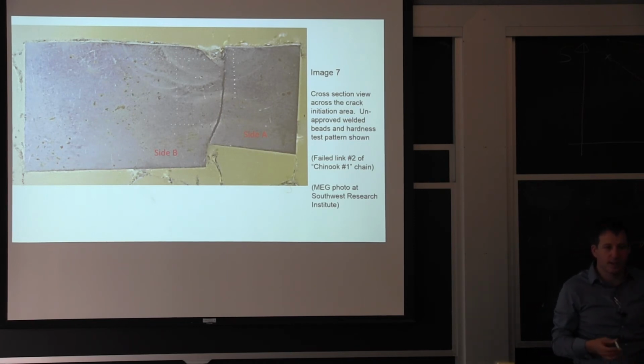So these chains had cathodic protection. And just seawater and cathodic protection was enough, since the steel was too hard, to start cracking, and the cracks grew for about a year and then eventually let go.